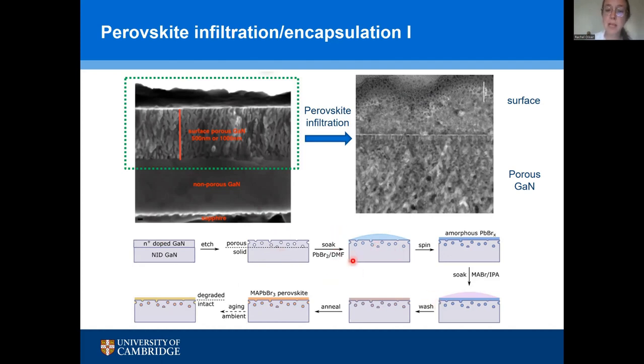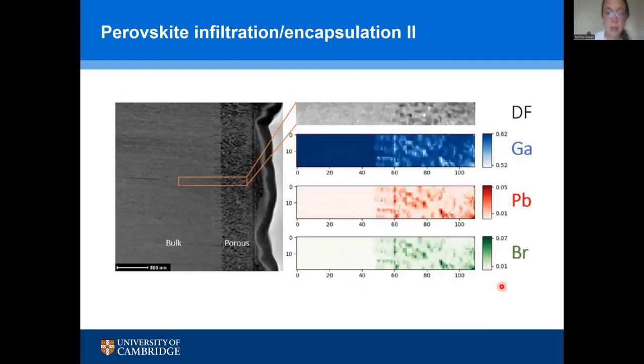So we developed a process for doing that, where we soak the porous gallium nitride in the precursor solutions for the perovskite material. And then the reaction goes on that forms the perovskite within the pores. We're using them almost like little test tubes. And if we look at that again in the transmission electron microscope, we can use EDX imaging, which is a composition sensitive technique. We can see here the bright areas are where the pores are, where there's less gallium. And in those same areas, we have little dots of lead and bromine, which is how we're identifying our lead halide perovskite. So we can show that we really have achieved this infiltration into the pores.